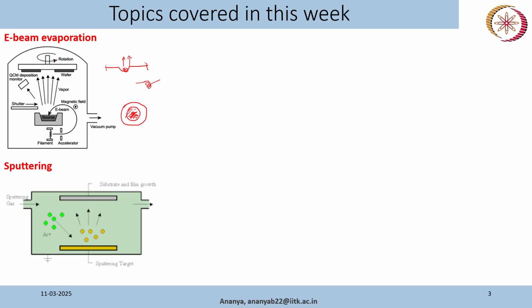Okay, and here you can see there is this rotation. We rotate this substrate holder, we call it a substrate holder, the wafer is our substrate. We rotate it so that we get a uniform deposition. Now there is another component, the shutter. Say you want to deposit a very thin layer, say 50 nanometer of nickel on top of your wafer. You will control your deposition rate such that it is slow, because if the deposition rate is very high, even if you close the shutter, your thickness will vary significantly. So you will maintain a very slow deposition rate, and then you will close the shutter,